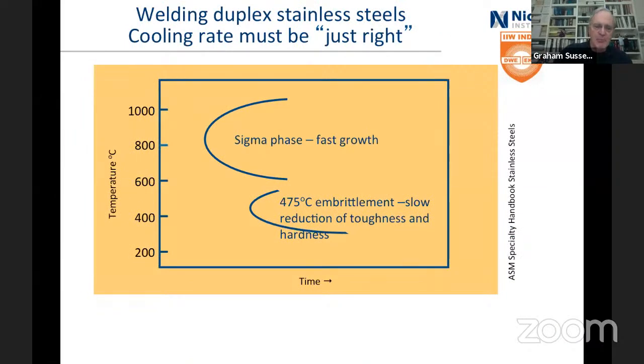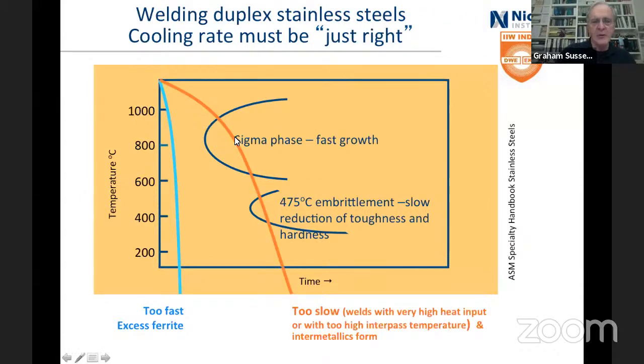So this is beating you over the head with it, but if you go down too fast, if you cool really, really fast and work at it hard, then you just don't get any austenite, too much ferrite, and so you lose the benefits of having a duplex. If you take it very slowly, then you go down through the sigma phase. So very high heat input would do that, or really high interpass temperatures, and you'll get the intermetallics there and you'll lose some toughness down there. And really, this is the sweet spot. You go down, you miss the nose there, but remember that this is really quite quick. So if you have repairs, that's a problem, because the time we're talking about along here is cumulative. If you make a mistake and have to repair it, wow, that's a problem.